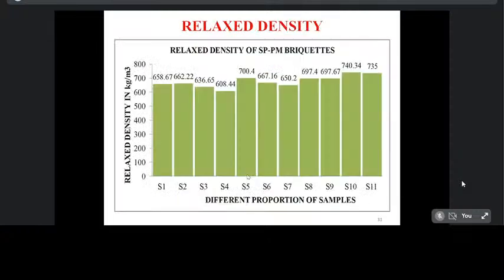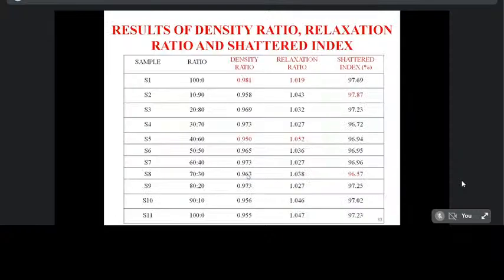So the relaxed density of the sorghum panicle PM millet briquettes is shown here. The minimum value was achieved by sample S4 as 608.44 kilogram per meter cube, and the maximum value of the relaxed density was achieved by sample S10 as 740.34 kilogram per meter cube. So here this table shows the density ratio, relaxation ratio, and shattered index. Density ratio also varied from 0.950 to 0.981, because a density ratio of less than 1 is a good quality briquette. Here all the produced biomass briquettes are less than 1.